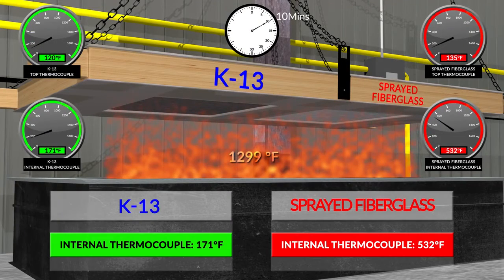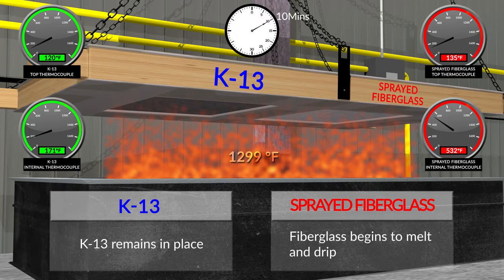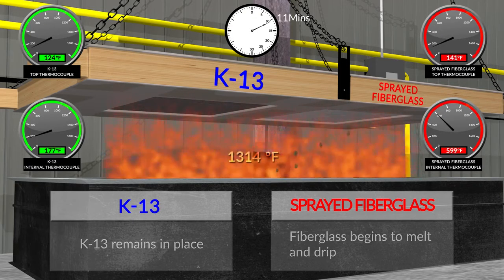At 10 minutes, K-13, the internal thermocouple is 171 Fahrenheit. Sprayed fiberglass, the internal thermocouple is 532 Fahrenheit. At 10 minutes, K-13 remains in place. Sprayed fiberglass, the fiberglass begins to melt and drip.